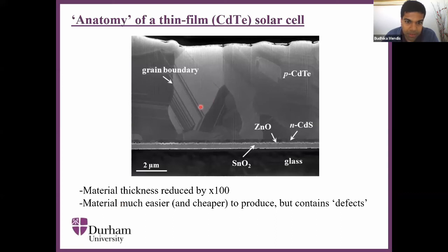What's more, these materials are very cheap to produce. They're very fast to produce. So First Solar, who produce cadmium telluride solar cells, they could make a full device in a couple of hours. So it's a very fast process that is cheap and able to produce solar panels on a mass scale. The disadvantage, however, is that if you look at this micrograph, you will see that your light absorbing material is not uniform. You can see that it's got a lot of features. This feature is what we call a grain boundary. These grain boundaries represent defects in the atomic structure. And these defects are unfortunately quite commonplace in thin film solar cell materials and are what is currently limiting their efficiency.